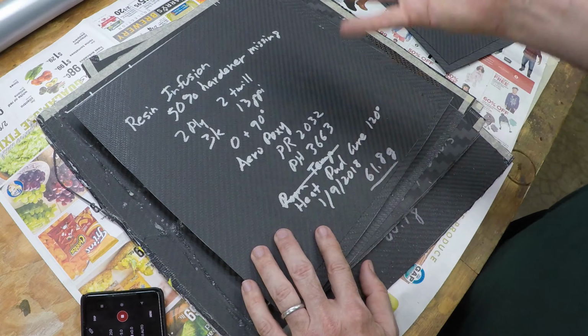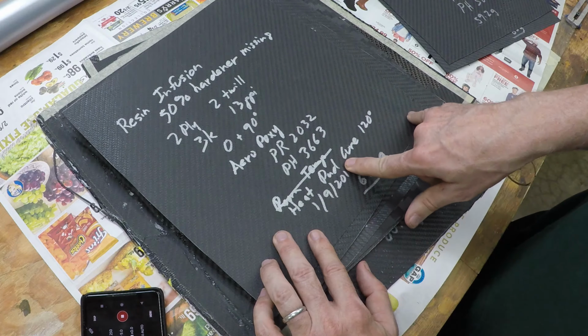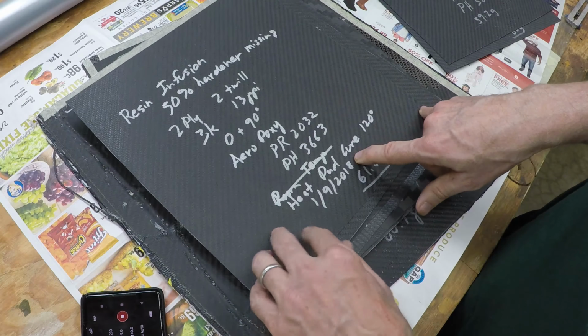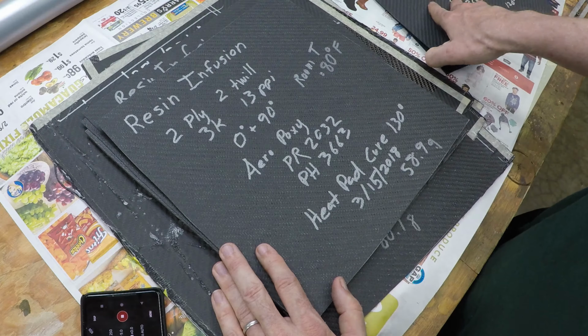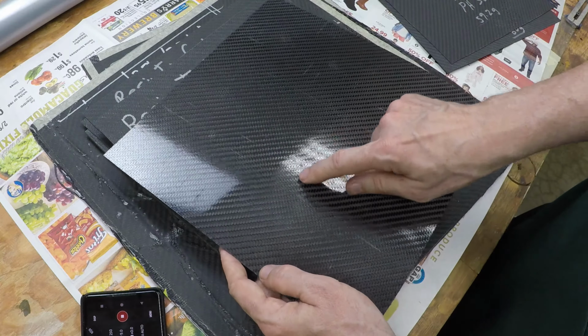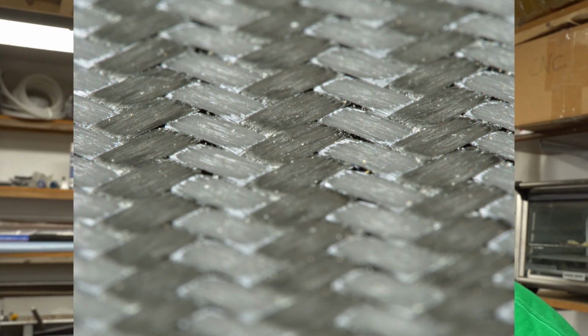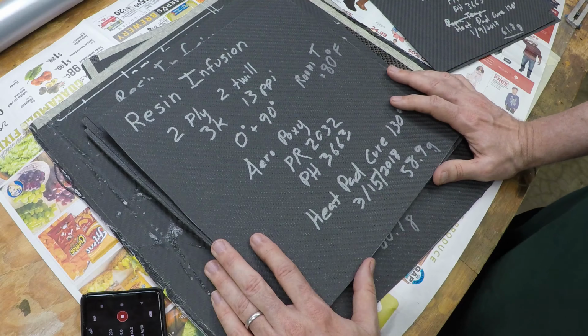Another thing that I tried on this, which was really pointless at this point, is I put a heating pad on this. I heated this up to 120 degrees Fahrenheit. Now here's where I started getting serious about trying to figure out why I wasn't getting a good surface finish, because I had noticed on all these samples over here, I was not getting a good surface finish. Let me show you a photo here of what the surface finish looks like. As you can see in this photo, I'm not getting the crimps filled on the mold side of my sample. So this was my first test of trying to figure out why that is.